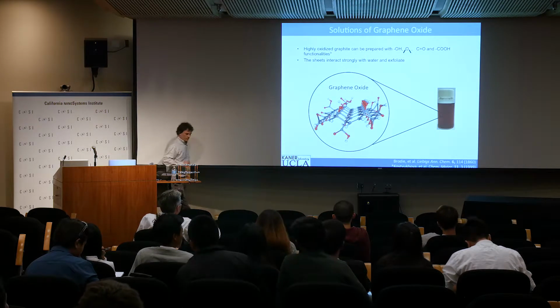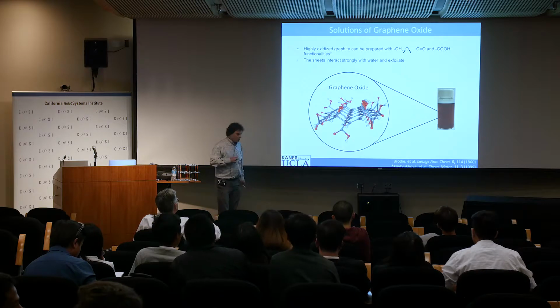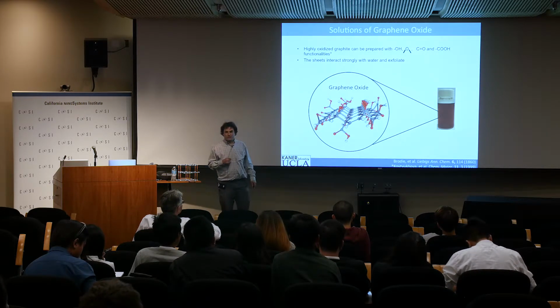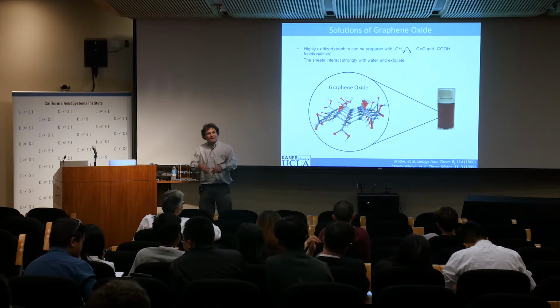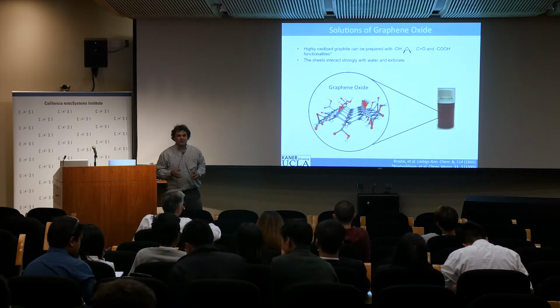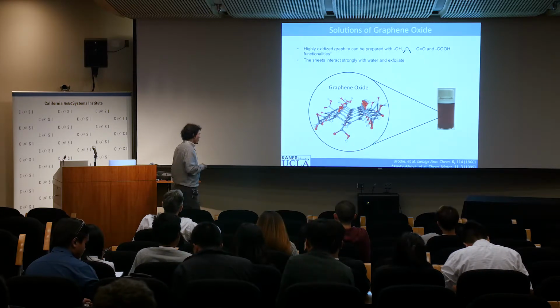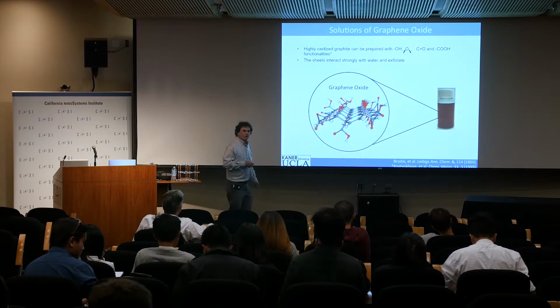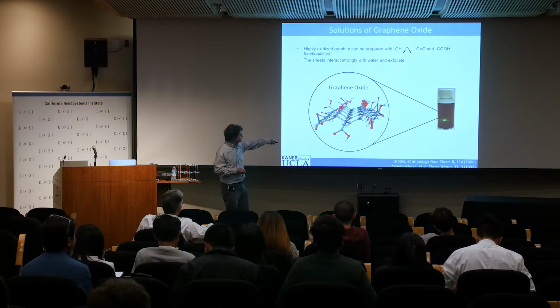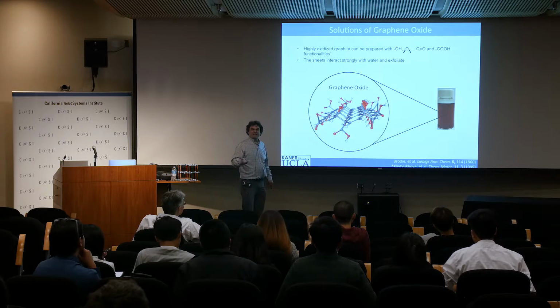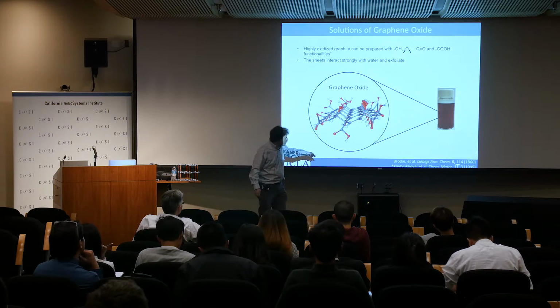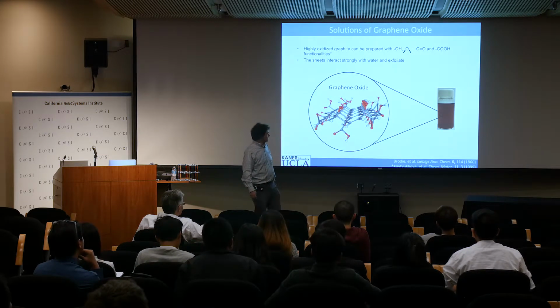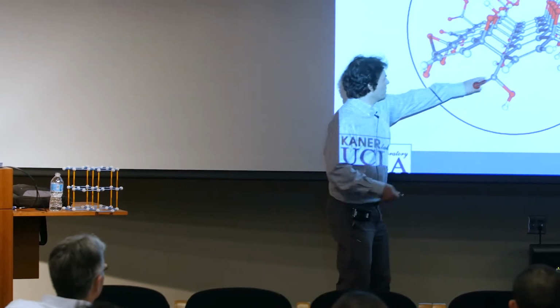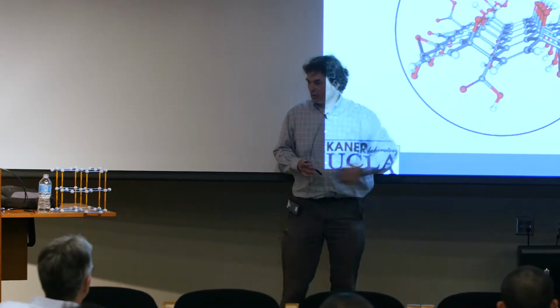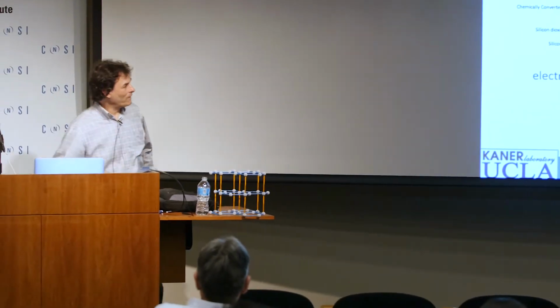Now, after Novoselov and Geim did their work, we started working on graphite oxide. You can take graphite, and it's been known for 150 years that if you oxidize it with certain acids, it forms a dispersion in water. So here it is in water. And when I say it's over 150 years old, here's a paper from 1860 on graphite oxide. And graphite oxide is nothing more than a sheet of graphene with carboxylic acid groups, hydroxyls, and epoxides. The question is, how do you get this back to graphene?